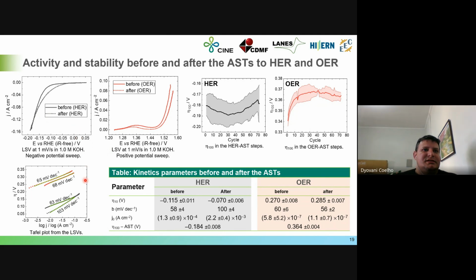But the interesting thing here is that there is a huge change in the Tafel coefficient, which means that the mechanism of the reaction changed too. So after the accelerated stress test, the mechanism of reaction changed for the hydrogen evolution reaction. But for oxygen evolution reaction, it is not observed. The Tafel coefficient here is more or less the same, which means that the reaction mechanism is the same. And the overpotential for the reaction increases a little, but just a little. But the interesting thing here is, if we just look at the overpotentials during the accelerated stress test, this catalyst could be claimed as stable.